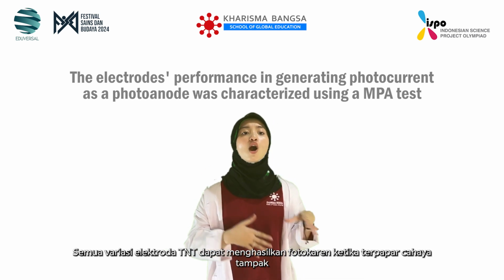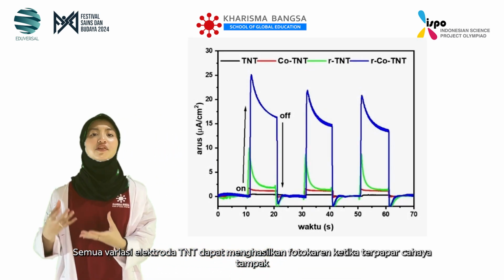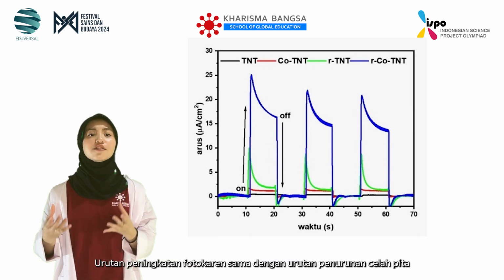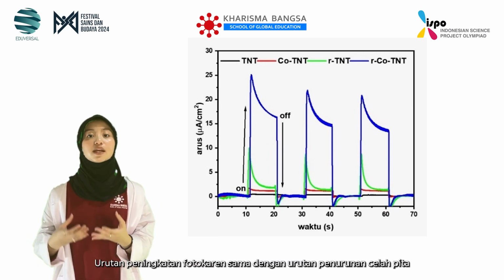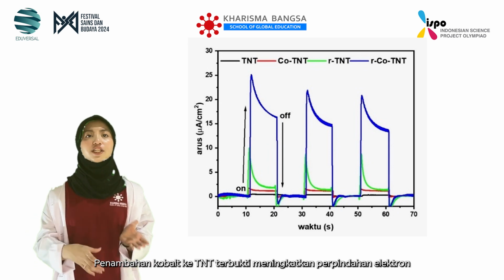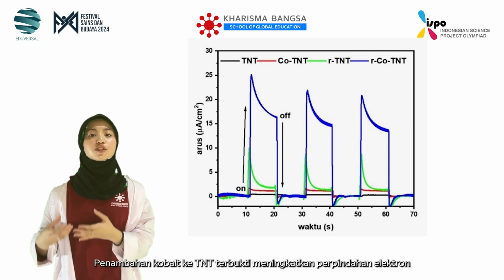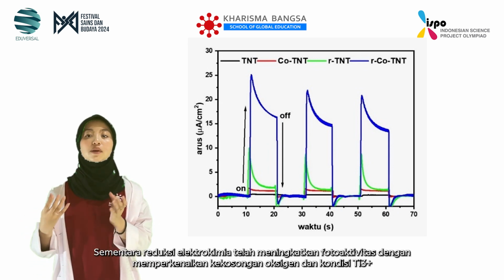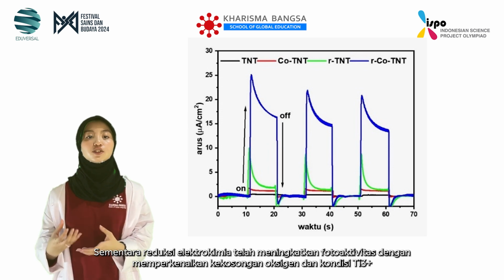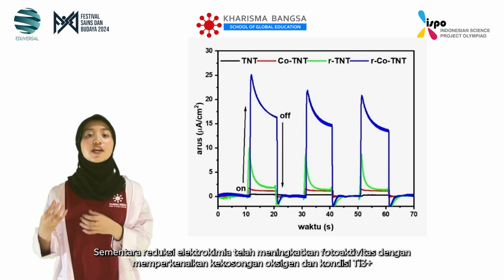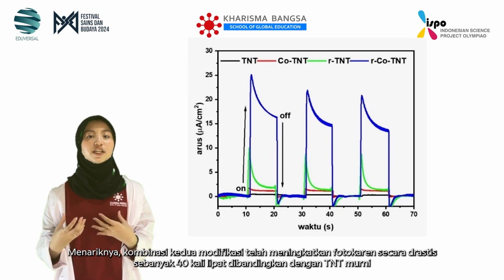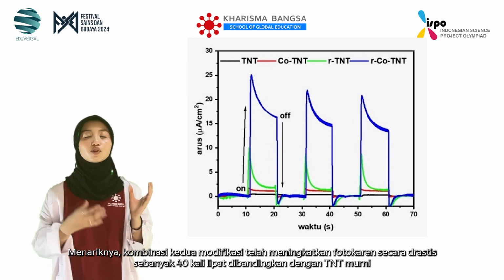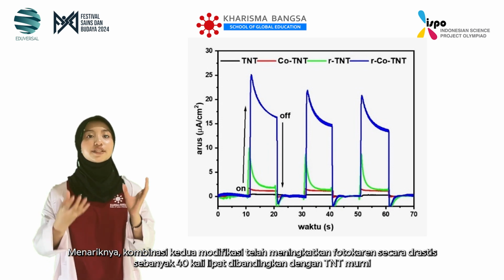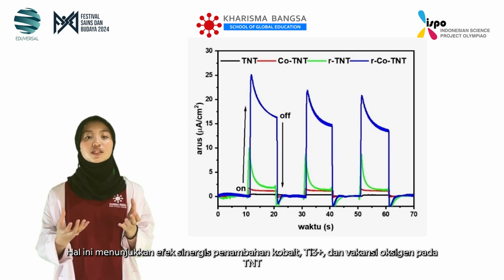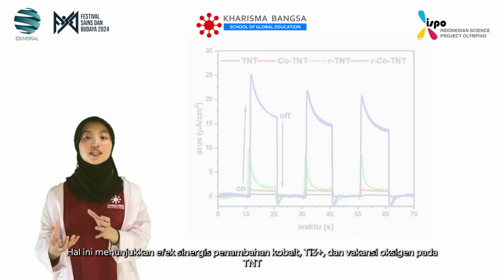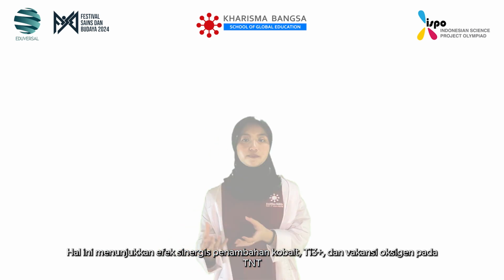seen from the graph. All varieties of TNT electrodes could generate photocurrent when exposed to visible light. The order of increase in photocurrent is the same as the order of the lowering band gap. The addition of cobalt in TNT improves the transit of electrons, while electrochemical reduction improves the photoactivity by introducing oxygen vacancy and Ti3+ states. Interestingly, the combination of both modifiers gives a drastic 40 times photocurrent improvement compared to pristine TNT, indicating a synergistic effect of cobalt presence, Ti3+, and oxygen vacancy of the TNT.